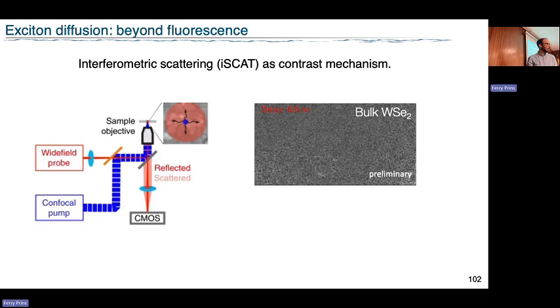So the presence of a carrier changes the refractive index of your material locally by a tiny bit. But apparently, and I'm showing you here a movie of bulk tungsten diselenide, this is not emissive, right? This is a multi-layer transition metal dichalcogenide. This is delay before the laser pulse arrives. This is pump-probe.